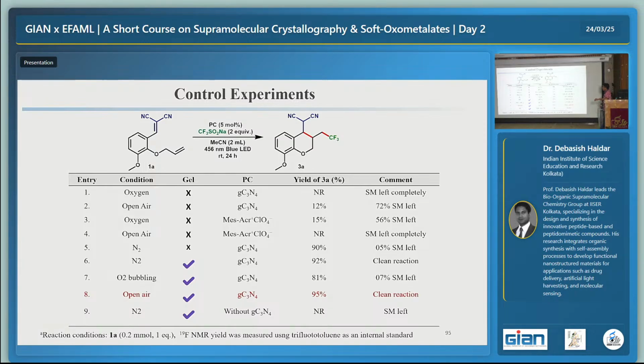When this is in oxygen without gel, there is almost no reaction. In open air, almost no reaction. But in the presence of gel, we are getting 95% yield in open air. That means oxygen cannot permeate through the gel, and the gel acts as a confinement, and the gel can do this reaction, and we are getting 95% yield. So very clean reaction.